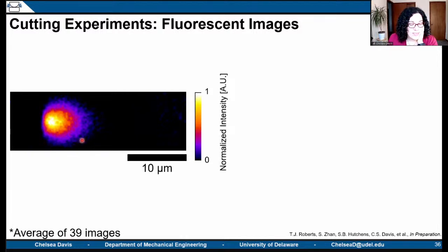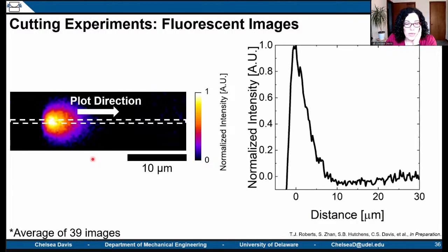And what you can see if we rescale our heat map so that we can highlight just the activated portion of mechanophore ahead of our propagating crack tip, we can say that we have approximately 10 microns, maybe a little less, of a large deformation regime that we're able to observe. And if we go through and plot the intensity of this, we can get a little more quantitative with it and actually say how far from our blade we were able to observe fluorescence activation in our material.